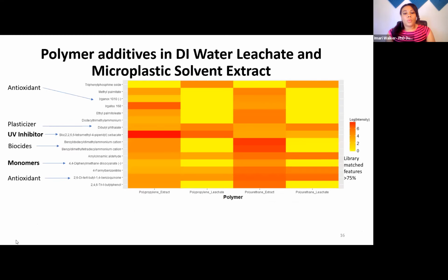So one thing that we also were able to find was, when comparing the extract of the plastic to the leachate of the plastic, there were compounds that were more likely to stay associated to the polymer, and a few of them were actually likely to migrate out into water. Secondly, there were different compound classes that were common to different plastic types, like these antioxidants, plasticizers, this UV inhibitor, to biocides and monomers of the actual polyurethane.